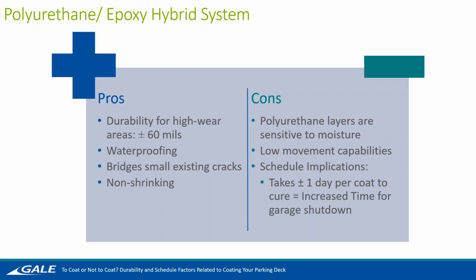Some of the cons are that the polyurethane layers are sensitive to moisture. So the top coat and the wear coat are sensitive to moisture. They have low movement capabilities, and it takes at least a day for each coat to cure, and it increases the time your garage is shut down as well.